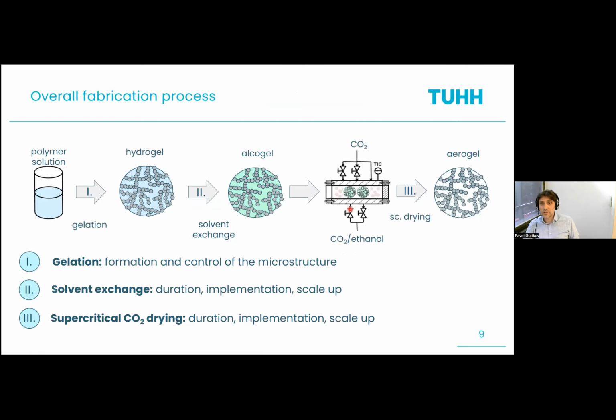Summarizing this short introductory part, we have basically 4 steps, or 3 steps, if you will. We have a gelation step. We produce a solid but still wet material. Sometimes we have to substitute this water, if the reaction goes in water, by an alcohol, for example, and then we extract the solvent alcohol to make a porous replica of the structure here. And of course, as a chemical engineer, you may ask: all right, here's the chemistry part, but solvent exchange and supercritical drying do sound like 2 extraction processes, and this extraction takes place within the porous body. So it has the basic balls and the pores and the channels, which make the process diffusion controlled in many cases.